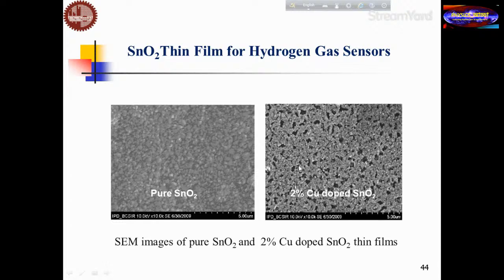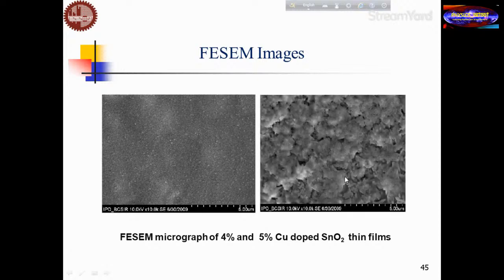Porous structure is there. And again, if you see the higher concentrations, the 4% and the 5%. At 4%, you see that it is highly pinhole free, compact, dense, and with homogeneous distribution. But for 5% here, you see some holes and cracks and some porosity is there.